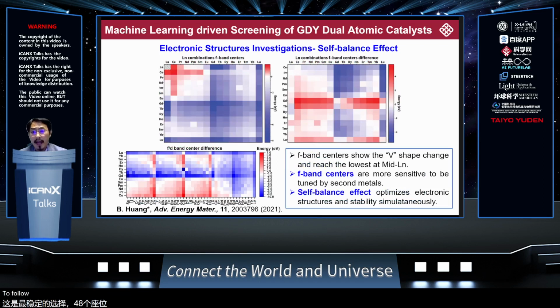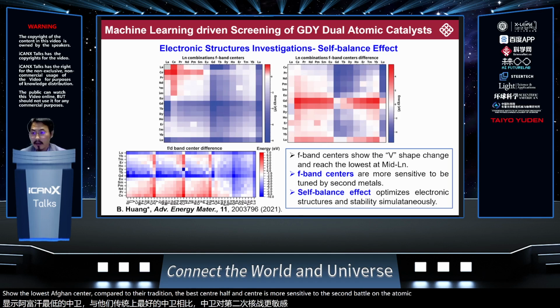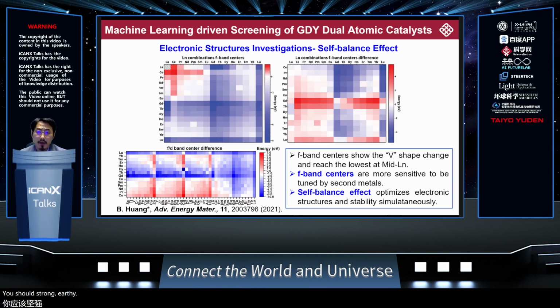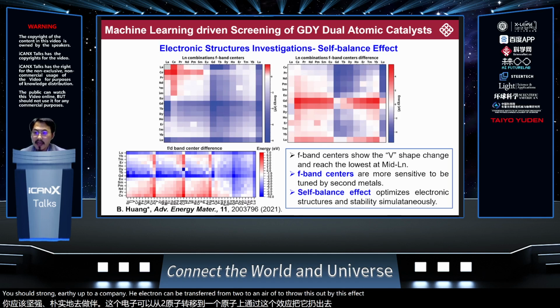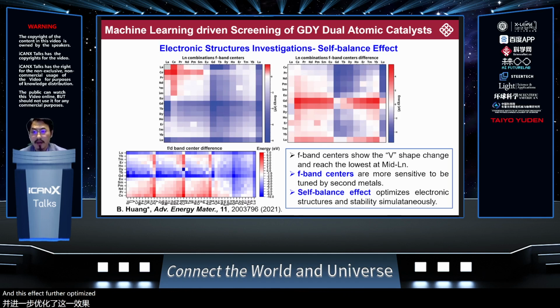To further understand electronic modulation, we propose the f-band center for the first time. The f-band center shows the V-shaped valley trend, and the middle lanthanide metal shows the lowest f-band center. Compared to the traditional d-band center, the f-band center is more sensitive to the second metal on the atomic catalyst. Due to the strong f-d orbital coupling, the electron can be transferred from d to f orbital through the self-balance effect. And this effect can further optimize both electronic structure and thermodynamic stability.